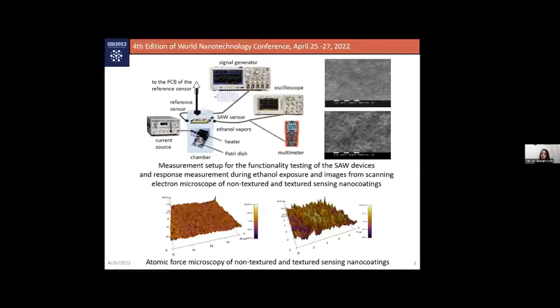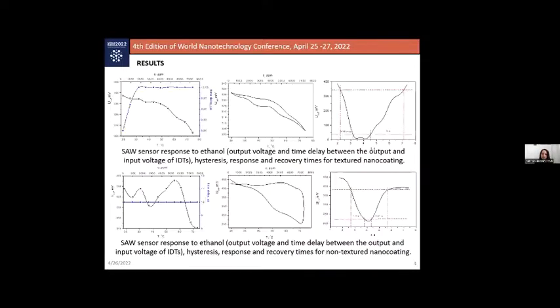And as you can see here, in the images from the scanning electron microscope and atomic force microscope, the texturing of the sensing film is visible after application of the acoustic wave. The roughness of the surface increases, which facilitated the adsorption process for the analyte. The morphology change affected the main sensing characteristics: the sensitivity, dynamic range, hysteresis or reproducibility, and response and recovery time.